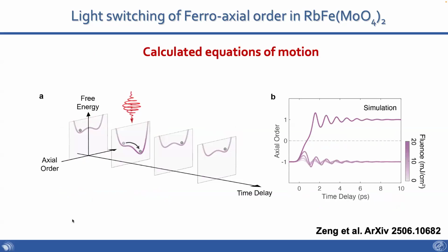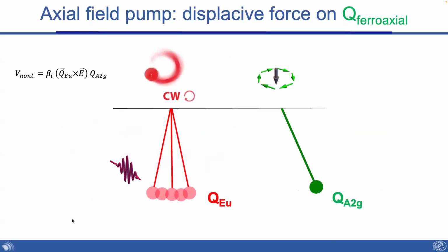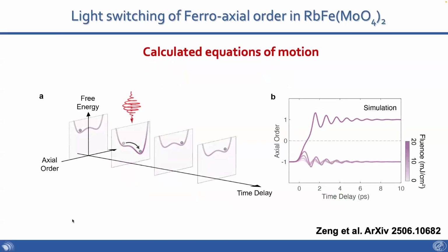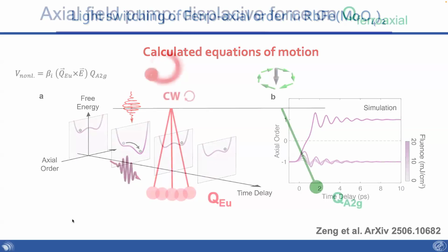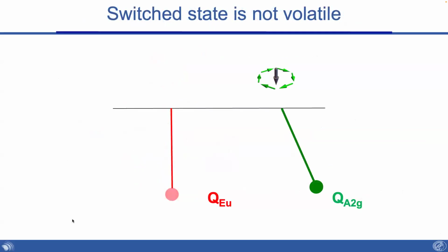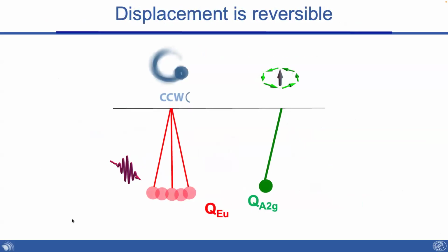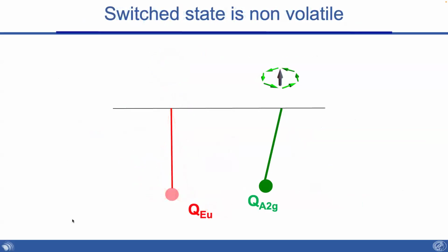These are again equations of motion calculated by Michael Fechner, whom I introduced before. There is a threshold above which I potentially can switch between these two states. So above a certain fluence, I should be able to do this. All right, so this is what you are asking, Laura. So I'm moving the auxiliary pendulum in circle, and this is coupling to the QA2G mode. What's very nice about this is that according to the equations of motion, when you're done pumping, the mode stays there. So it should be non-volatile. So you stop pumping it, and the state should stay there. Then you can come with a pulse of opposite rotation, and you should generate a force in the opposite direction. You stop pumping it, and at least what the theory says is that you'll be able to really use the circular light.